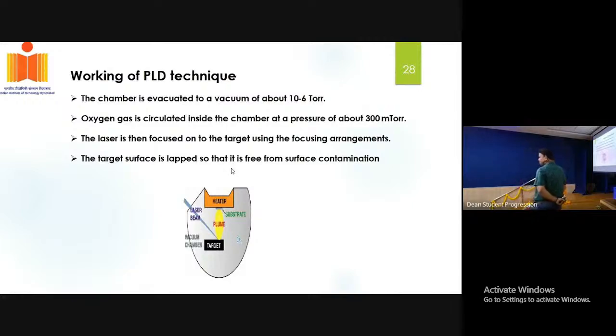Another important physical vapor deposition technique is called pulse laser deposition. Again, the chamber is evacuated to very high vacuum. There is a difference between high vacuum and ultra high vacuum. High vacuum means you need to evacuate up to 10 power minus 6. Ultra high vacuum means up to 10 power minus 9 or minus 8. You need to evacuate the chamber first so that the air molecules can be removed. It can be any physical vapor deposition technique, the thermal evaporator or the sputtering or the PLD. You need to remove all the air molecules from the chamber.